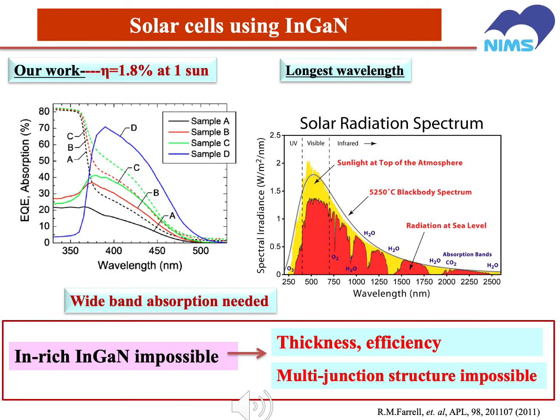So next I will introduce our work on the solar cell using indium gallium nitride. And the typical structure for the semiconductor solar cell is like this. Typically a p-n junction is utilized, and then the active region is inserted between the p-n junction to fabricate this solar cell. And in our work, now we can achieve the conversion efficiency around 1.8%. And for the other groups, the conversion efficiency is still lower than 2%.